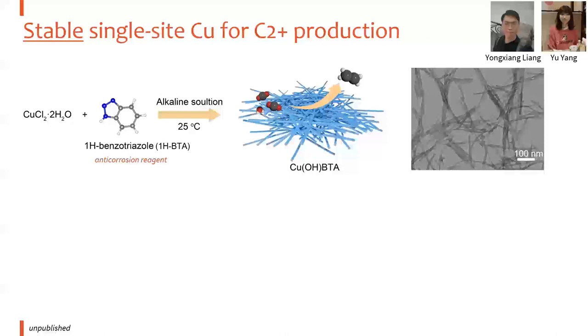Our starting point is this material, copper BTA molecular. The reason we use this one is that we are thinking if we can find a chemical that is ultra stable during electrochemical reducing conditions, that means it may not undergo aggregation of copper from single sites into copper nanoparticles. So we choose the BTA ligand, which is the anticorrosion reagent. The reason is that the coordination ability between this BTA molecule and the copper is super strong. So it's difficult to reduce the molecule, so that this molecule can form a very dense layer on top of the surface to protect the copper from further corrosion. So we are thinking that this material may be stable under electrochemical reducing conditions.